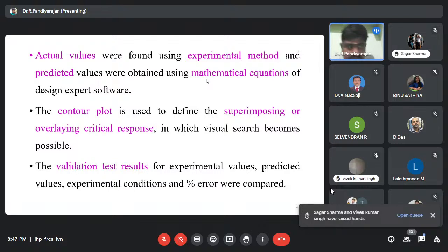Once we develop the mathematical equations, the contour plot is used to define the superimposing or overlaying of the critical responses, and the visual search becomes possible. Once we find the optimum solution for the friction stir welding process parameters, once again we have to test it with experimental validation test results. The validation result is very important. Once again, with 3 to 5 trials, we compare the experimental and predicted values, and also find the percentage of error. If the percentage of error is less than 5%, then definitely we can use the optimum process parameters. It produces good quality welded joints.